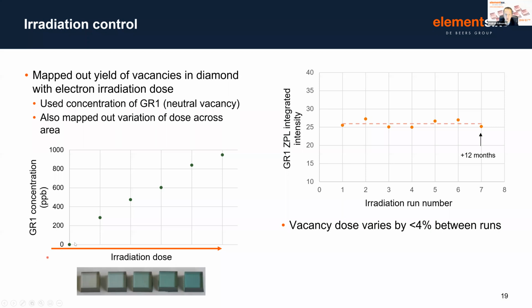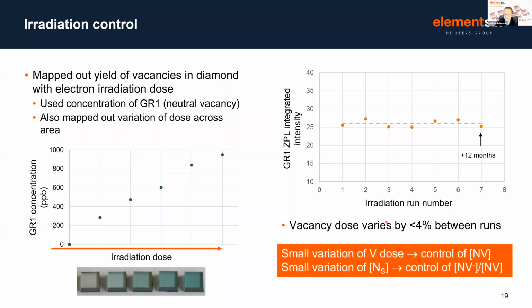And the second thing that we looked at was how reproducible the vacancy dose was. And we looked at this over a period of 12 months in different irradiation runs, and it varied by less than 4%. So again, the news is fairly good, we would expect, in terms of the reproducibility of this material.